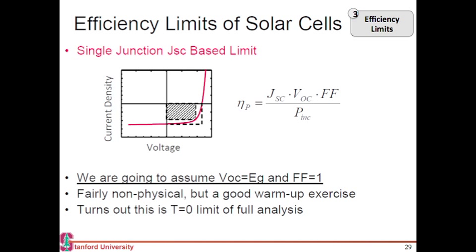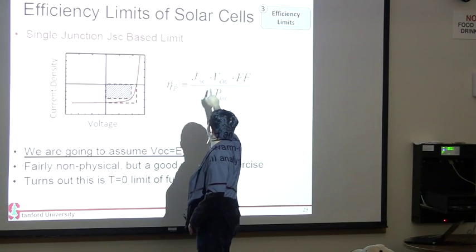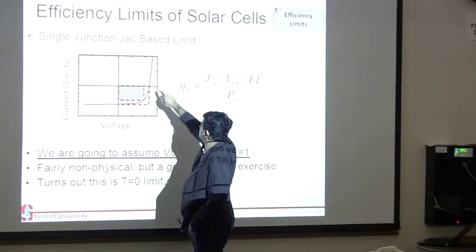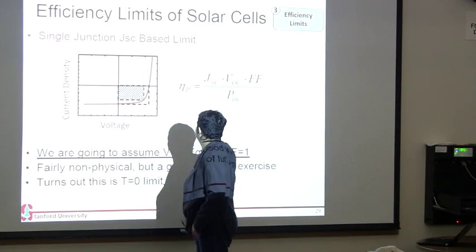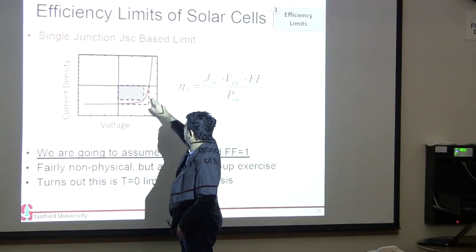So now I've emphasized that you need a density of state bottleneck, and you need selective contacts. And if you do that, the IV characteristics of your cell look something like this. Because of that photovoltaic action, you have this current in your fourth quadrant, and when you extract at a voltage over here, you get this much current. The important defining parameters are the short circuit current and open circuit voltage. Open circuit voltage is the voltage when you have zero current, and short circuit current is essentially this. And then you have a thing called fill factor, which is the area of this shaded rectangle versus the area of this larger rectangle.